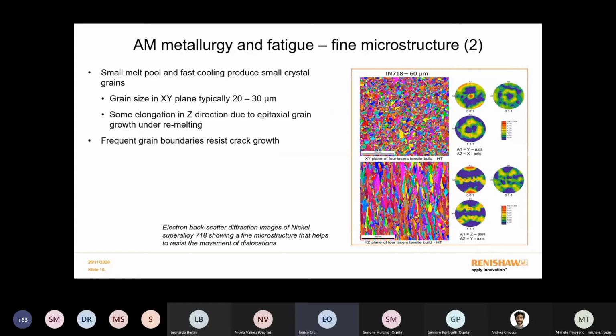We have small melt pools, and the microstructure and alignment of the metallic grains is very fine, specifically in the horizontal plane, while on the vertical plane, due to melting and remelting, sometimes we have elongation of the grain. Anyway, we're talking about grains in the region of 20-30 micron in the XY plane.